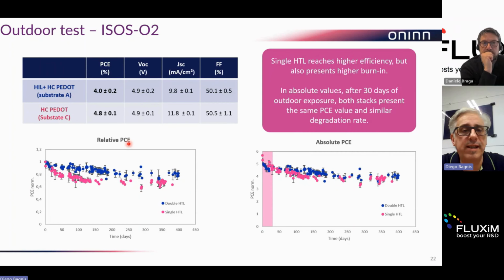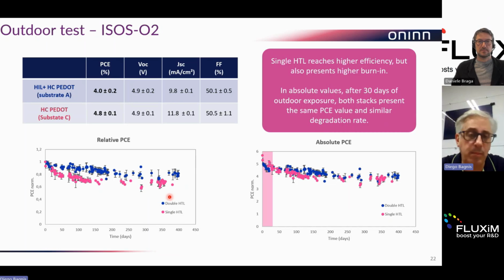On the other side, for the outdoor test, just to make some comparison between single and double HTL, this was one of the first tests, 1 year and a half ago, so the performance was slightly lower in that era. But just to show that when you want to choose the right condition, as I mentioned more than once, it depends on the application. This does not mean that using the HTL in a single layer to get the higher performance will be the best choice, because in this case you see that after just 30 days of outdoor exposure you find the same PCE outdoors whether it is single or double HTL. So depending on the application, depending on the optimization, it is possible to make the right choice for the application itself.